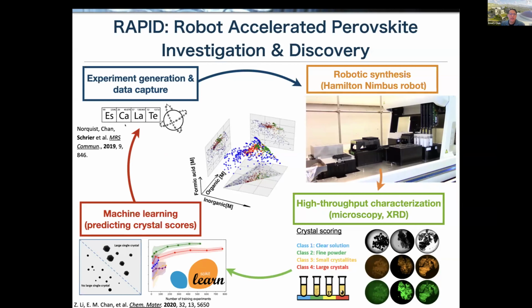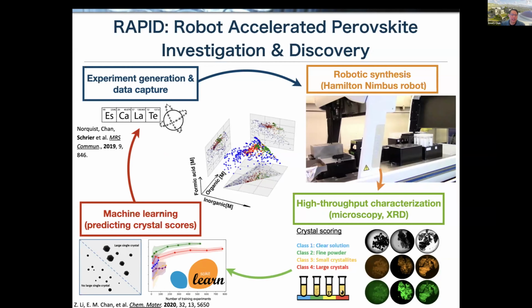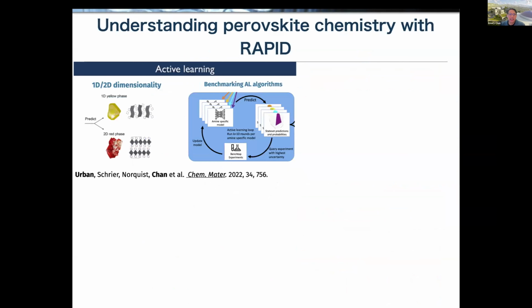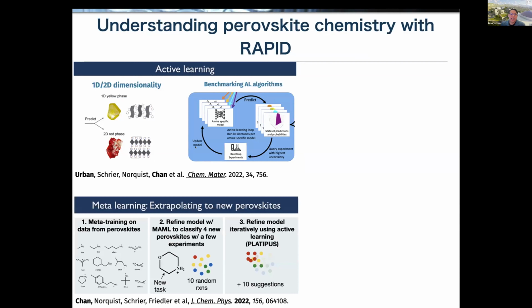So if you want, you can feed that information from your model back into the ESCALATE pipeline, which can generate new reactions to run that can update the model and make it more accurate. So this kind of sequential learning is often used in an active learning mode. So in active learning, you're updating your model to make it more accurate. And so in this case, we've used our RAPID workflow and active learning to learn models that can predict the dimensionality of perovskites. So in this case, the dimensionality means not the size of the particle, but the connectivity of the octahedral building blocks of these lead halide perovskites. We've also used active learning to study the ligands that can enhance the luminescence of these perovskite nanoparticles.